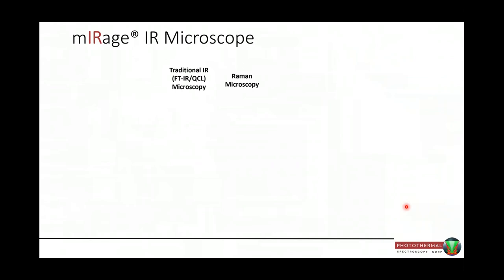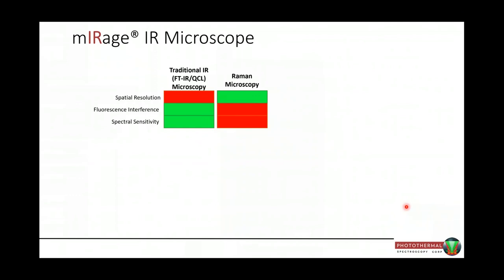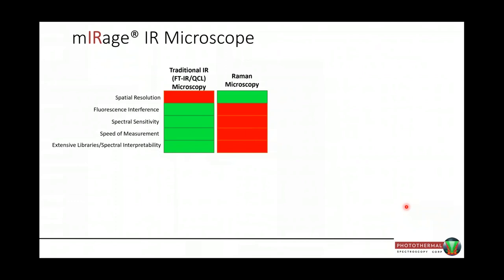So if you take a comparison between traditional IR, FTIR microscopy and Raman microscopy, you can see there are various advantages and disadvantages. Spatial resolution, Raman is better because it's a smaller spot size. If you have a fluorescent sample, IR works great. Raman has a problem. Spectral sensitivity, generally infrared is much more sensitive than Raman for most samples. Speed of measurement, infrared is generally faster than Raman. There are extensive databases of infrared spectra, not so extensive for Raman. But you can't measure very easily in reflection with infrared, whereas you can with Raman.